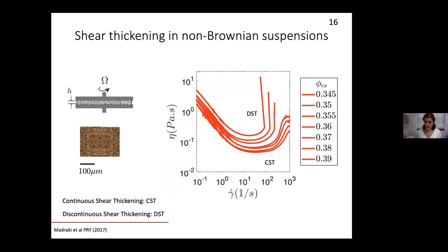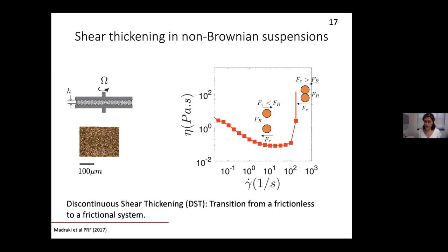So we have this system, and to explain why there is such a behavior, this is the theory to date, and it's as follows. For this particular material, when we have these grains of cornstarch in water, there is a repulsive force at the surface of these particles that prevents the particles from coming into contact with each other.